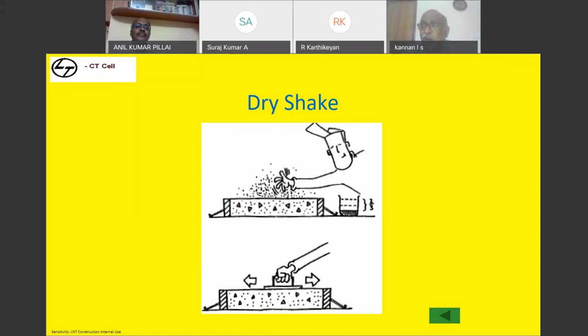This dry shake, whatever I am talking about, suppose I am doing a power trowel finish. Concrete is slightly hardened, so my power float will not move. I'll put some cement slurry, sprinkle it on the top and do the finishing. Or I have found some cracks, immediately I'll mix some cement slurry and put it over it. Or I'll spray some cement on the top. Hey, concrete is bleeding, put some cement on the top to absorb the water.